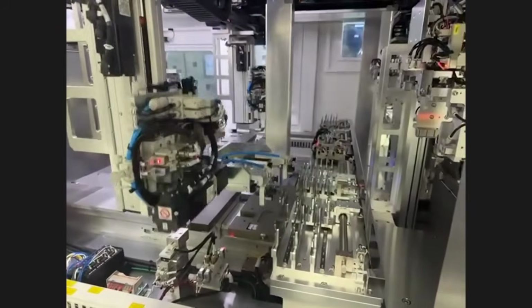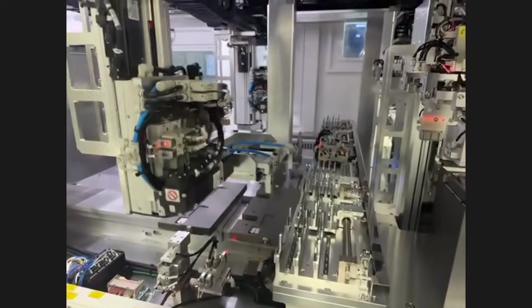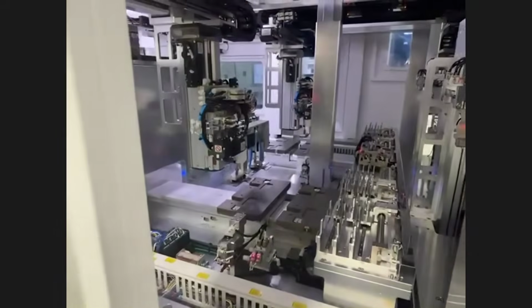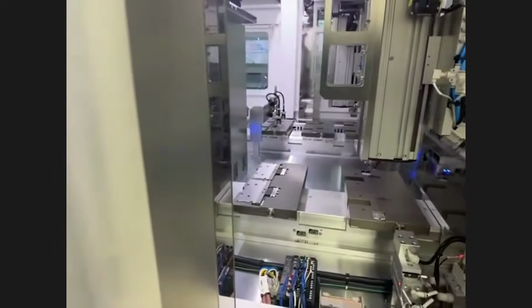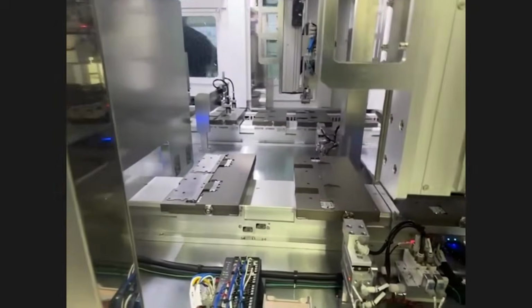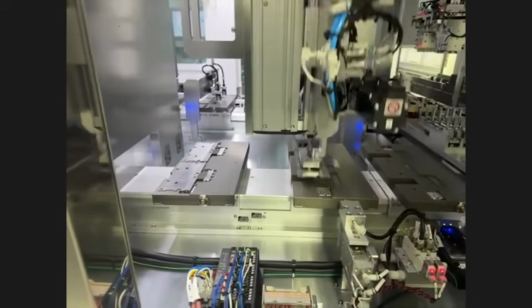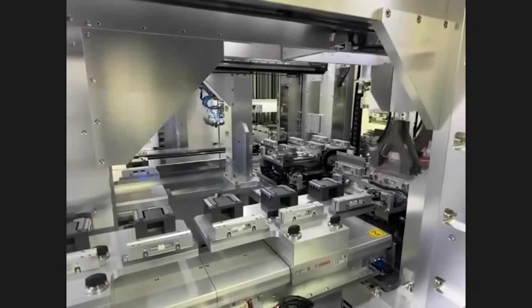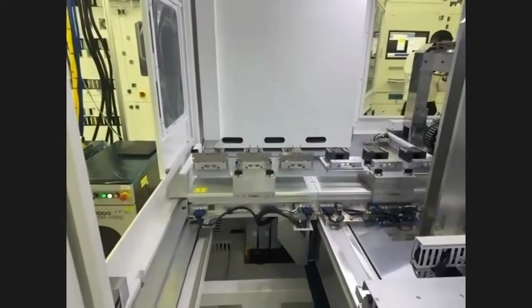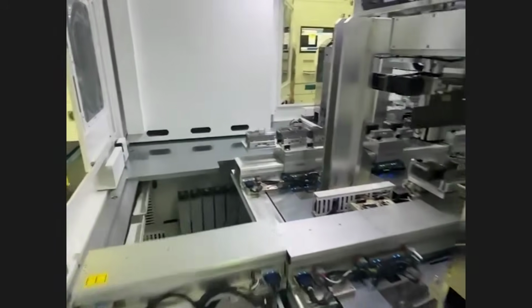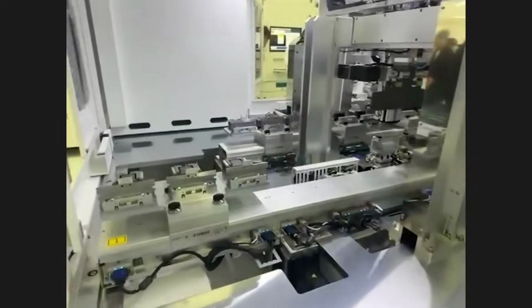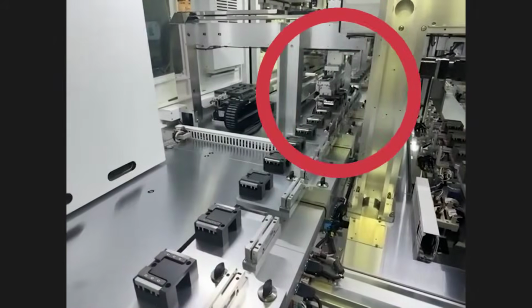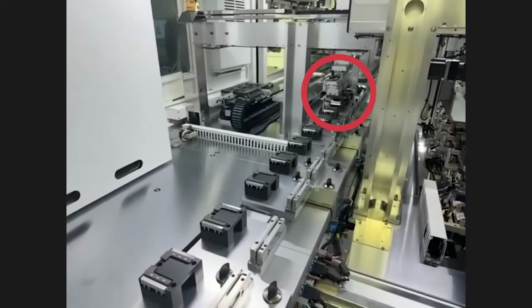To move past traditional lithium-ion cells that rely on jelly roll winding or cut-and-stack methods, Enovix uses a proprietary roll-to-stack process in which electrodes and separators are laser-patterned and directly stacked using high-speed automated tools. This precision assembly enables its silicon anode architecture, improving energy density and cycle life. Battery packaging and formation are largely conventional, with one key addition: a pre-lithiation step during packaging that introduces an incremental lithium source, improving formation efficiency and long-term performance.